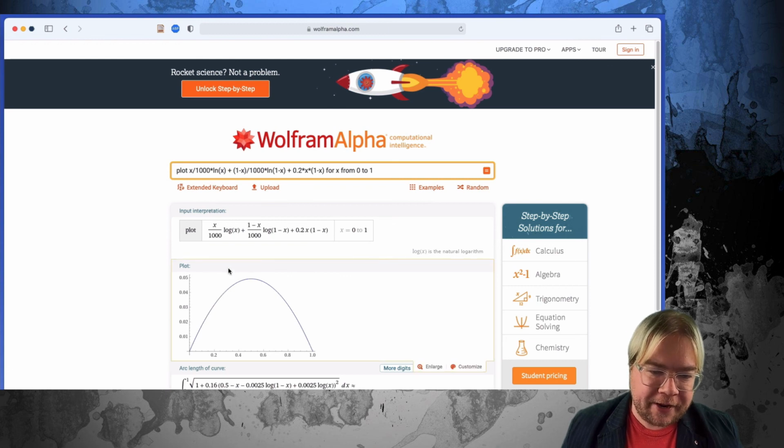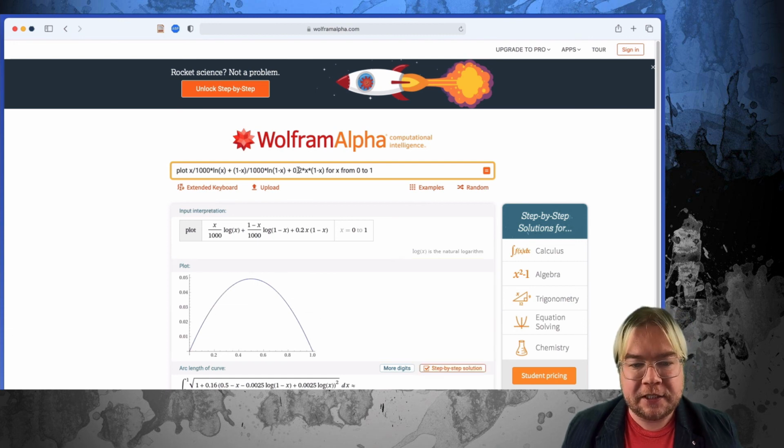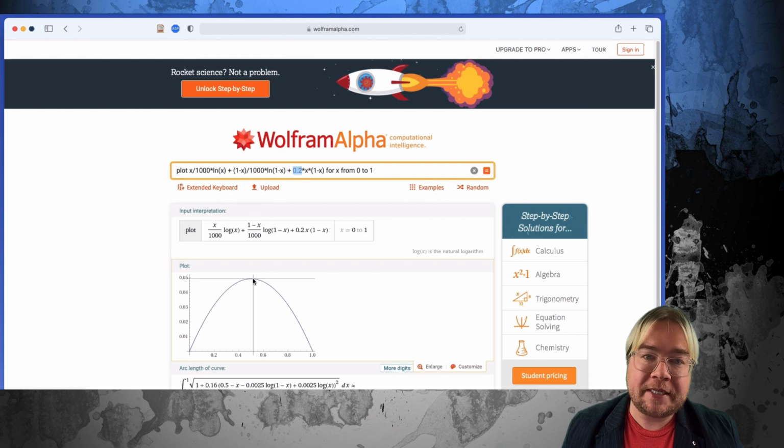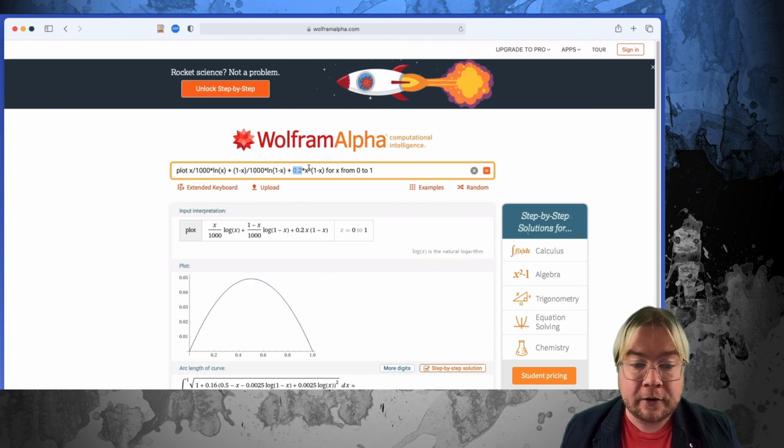So you see that now the free energy of mixing is positive for all values across this composition range. So mixing's not going to happen in this case. You see just a small interaction parameter has led to a free energy of mixing that's always positive. So these polymers will never mix together. And it's just because the entropy isn't helping them mix.